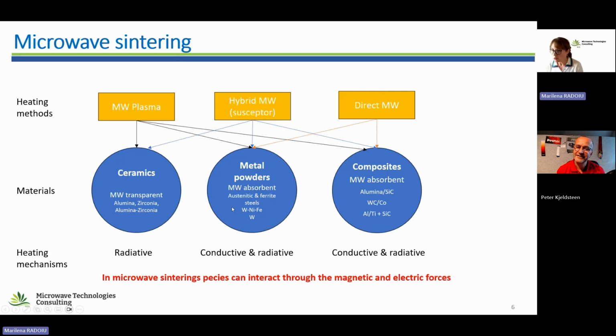In the literature, you have examples of the metal powders that have been sintered with microwaves, and you'll find steels like austenitic 316L, for example, and ferritic steels like 434L. I can't remember all of this, but both are sintered in microwaves, and tungsten powder is one of the most studied, along with all sorts of mixtures of tungsten, nickel and iron. There are so many examples out there. Then the third category is composites, where you can mix these transparent ceramics with a susceptor. A susceptor is a non-metal material which absorbs microwaves, and beta silicon carbide is one example. Tungsten carbide is another example, cobalt too, and you can make any mixture. So these are the three categories of materials, but how do we heat them?